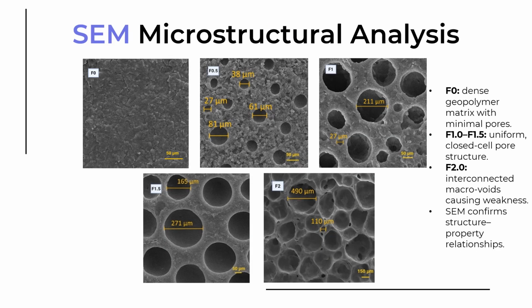For the SEM, we found that when foam percent was 0, there was a dense geopolymer matrix with minimum pores, and when we add foam between 1 to 1.5%, we have a uniform closed cell pore structure. And when the foam was more than 2%, there were interconnected macro voids causing weakness. So the SEM confirmed the structure-property relationship with the foam content.